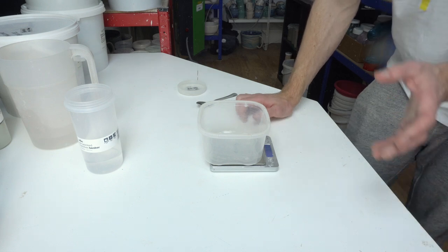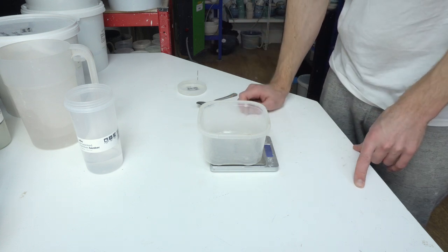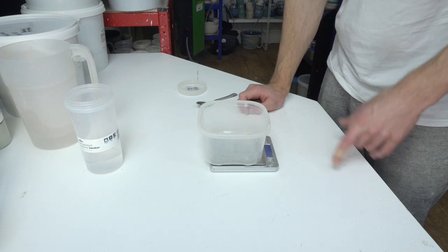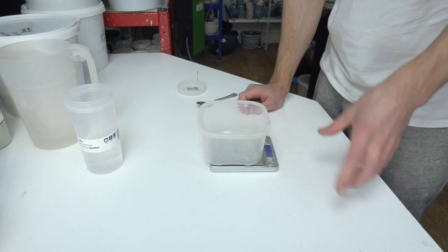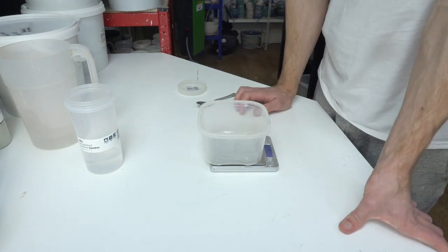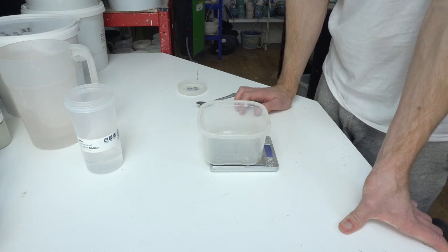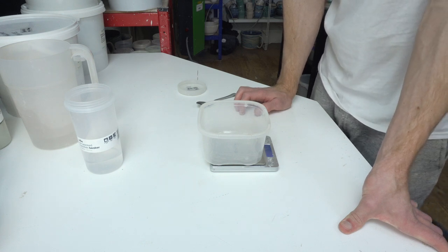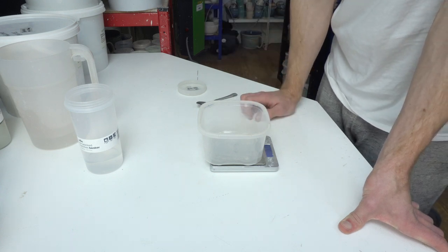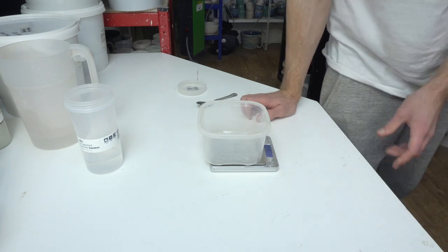The difference from a dried normal glaze is that you add water to that and it becomes liquid again. But if you sinter a glaze, you can add water to it and it will absorb some of the water, but it won't become runny again. Meaning you can chuck a handful of these chunks into another glaze and they will stay distinct. They are distinct lumps. So I will post the recipe for this that I'm testing.